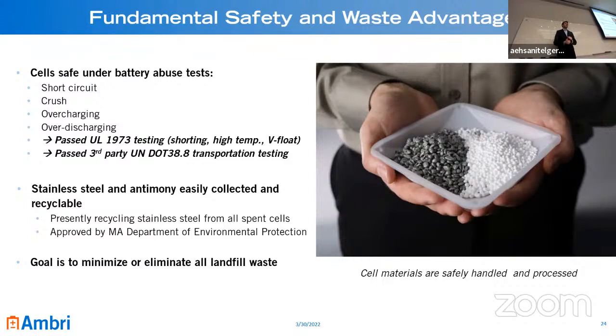If you short circuit our battery, it just discharges. It doesn't cause any safety event. Crushing: the batteries are in a thick stainless steel container, so that's very hard to do. Overcharging the battery and over discharging also doesn't create any safety event. In many batteries, if you overcharge them, you'll decompose the electrolyte, produce a gas, and that gas builds up pressure inside that cell, and then that can explode. And in many cases, that gas and the electrolyte is flammable, like in lithium-ion batteries, and then that electrolyte is what's actually catching fire, not even the electrodes in the battery. So our battery is immune to all of those safety issues.